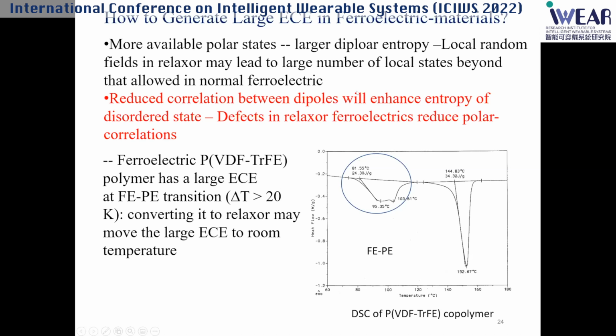So what happens is, if we can convert it into a relaxor material — because in the relaxor we have something called local random fields, they can lead to an even larger number of local states beyond what's allowed in the normal ferroelectric. And in the relaxor, because we have defects that further reduce the coupling between the polarization, they can further enhance the electrocaloric effect.